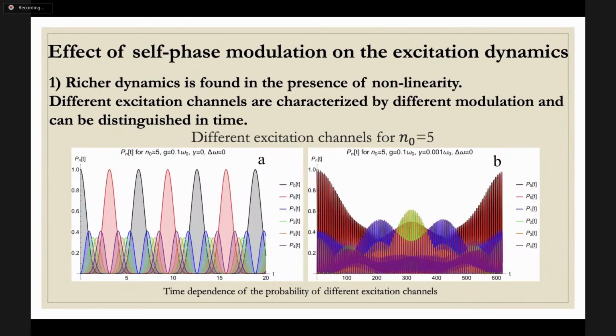So let's come to the results. In the case of absence of nonlinearity, different excitation channels are characterized by populations oscillating in time with constant frequencies and amplitudes, and no modulation of time-dependent behavior of the excitation probability can be found. However, even a small nonlinearity leads to the appearance of different dynamics of each channel and the appearance of modulation, while different channels are characterized by different modulation, which makes it possible to better separate the excitation of those channels by time. And this is very promising for practical applications.